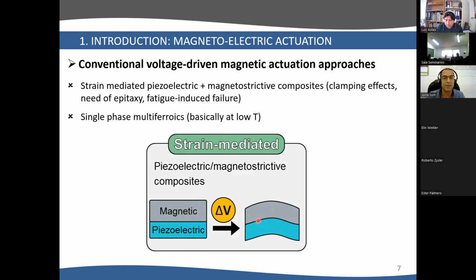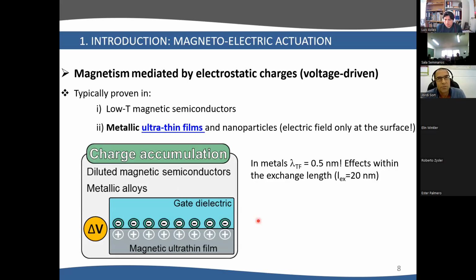So people have been searching for other mechanisms to control magnetism with voltage, and another one, for example, is charge accumulation. This was reported in the late 90s and early 2000s in low temperature semiconductors and metallic ultra-thin films, where people reported that if you apply voltage in alloys, for example, iron platinum or iron palladium, you can tune the coercivity of these alloys simply because the accumulated electrostatic charge can cause changes in the electronic band structure of the alloy. But to observe this effect, in particular for metallic films, you need to prepare very, very thin metallic films, like a maximum of 2 nanometers. Why? Because the electric field in metals is screened at the surface of the material. So this has limitations in terms of the type of layers where this can be observed.